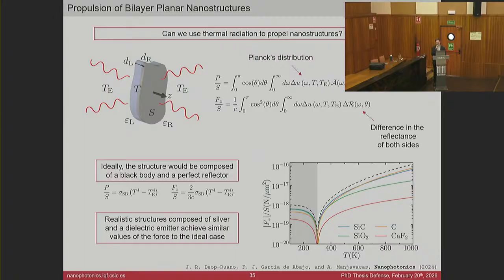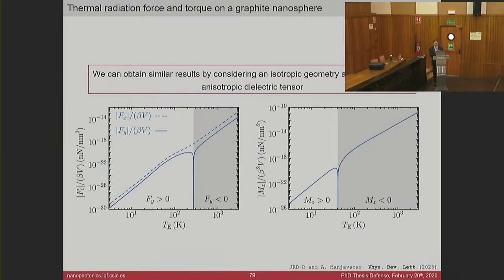In this work, yes. So this is actually something that I did, and you can actually make a sphere with an anisotropic dielectric tensor, and at the end of the day, this will give you some anisotropic polarizability that, when oriented in the proper way, so again, the principal axes of your permittivity tensor are not aligned with the Cartesian axes or with the velocity, then you will obtain off-diagonal components of the polarizability that will give rise to both forces and torques.